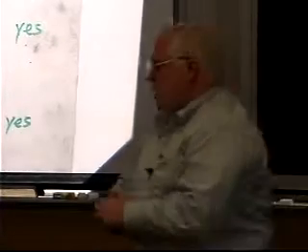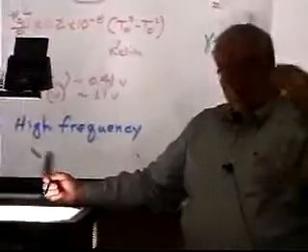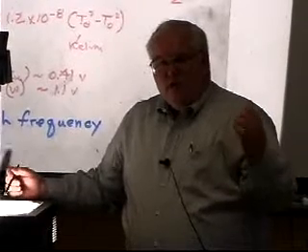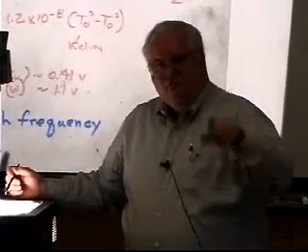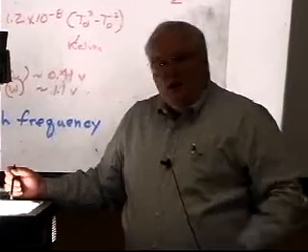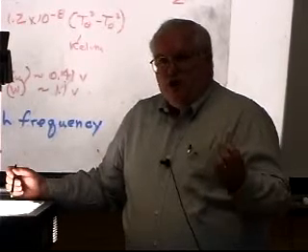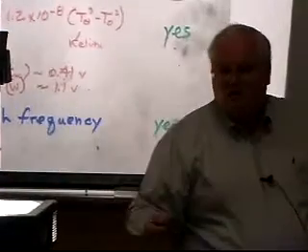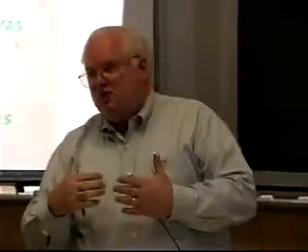In fact, on some welding power supplies, particularly when we're welding aluminum, which has this refractory oxide, I mentioned yesterday how we often gas tungsten arc weld aluminum with AC power, because we want to take care of cleaning off this refractory oxide. You often will lose the arc in aluminum because the oxide becomes refractory and you can't sustain the arc. So they actually have a high frequency overlay on a gas tungsten arc welding power supply. You flick a switch and they generate a lot of RF noise. If you go down to my lab with the radio on and someone wants to weld aluminum with the high frequency overlay on, the radio goes berserk and all you get is static, because you're generating all this RF noise.